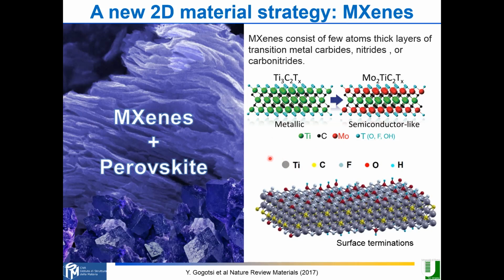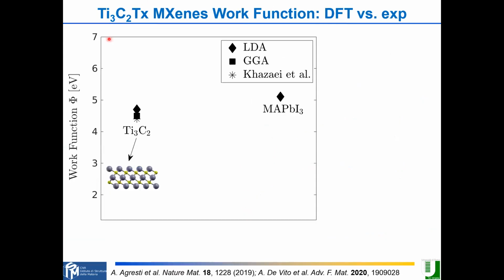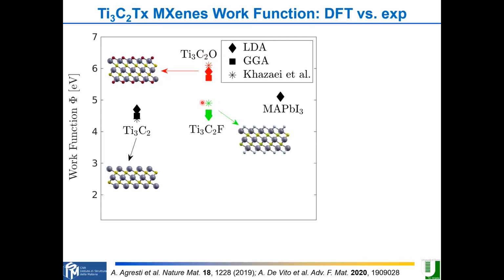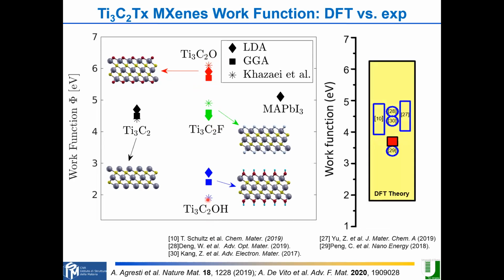Why this is very important, let me show you in a moment. Let's plot the work function, calculated by density functional methods. This is, for example, for the bare, non-functionalized Ti3C2, the simplest MXene, with a work function between 4 and 5. Now, if you put oxygen as a termination on the surface, you move the work function up to 6. If you use fluorine, it is between 4 and 5. But if you use the hydroxyl group, you can go down to 2 electron volts. So we have a system, the MXenes, where depending on the functionalization, you can tune the work function from 2 up to 6 electron volts.